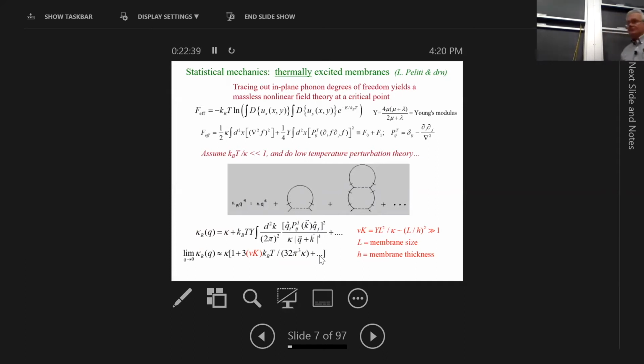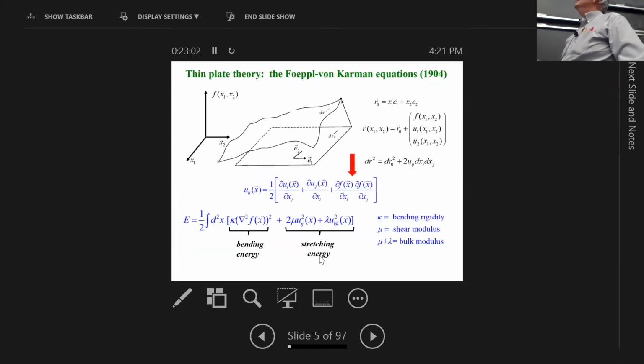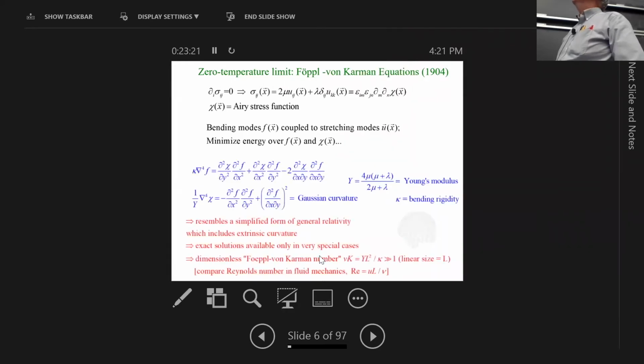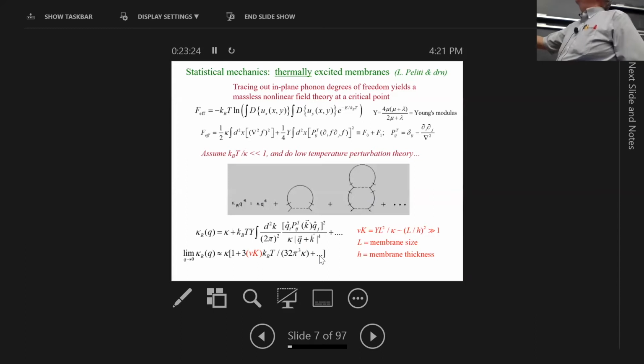And now you can ask what happens when you try to do finite temperature stuff, not 0 temperature stuff, do the statistical mechanics of this problem. And it's a challenging problem because it's so nonlinear, et cetera, but you can get rid of the in-plane phonons. And the reason, if I go back a little bit here, is these in-plane phonons, if you just square them and stuff, they only occur quadratically. So by doing some Gaussian functional integrals, you can just get rid of those phonons and focus down on what happens for the remaining degrees of freedom.